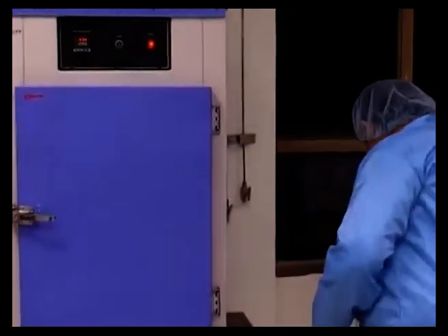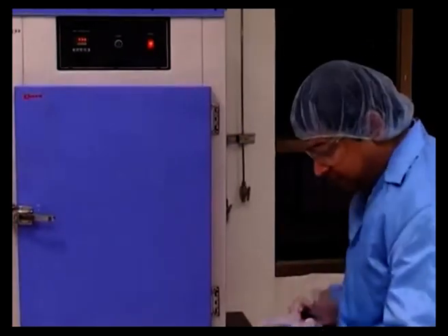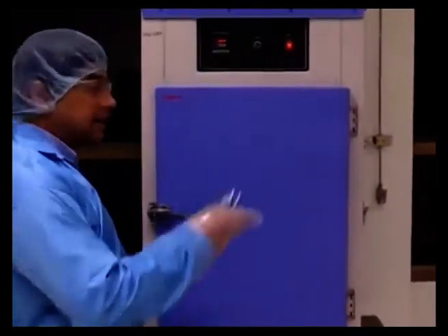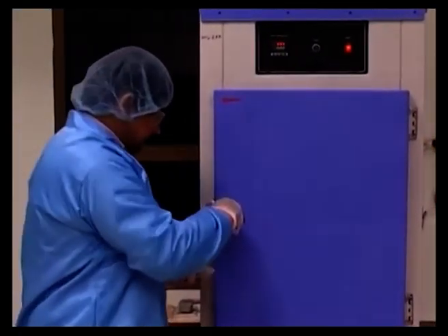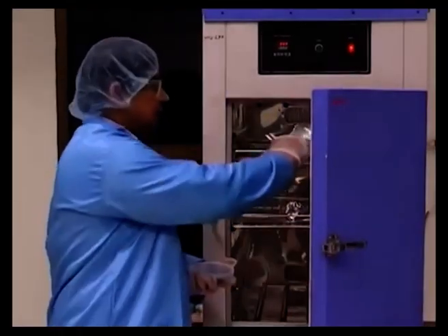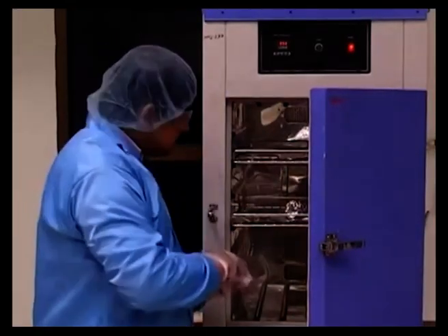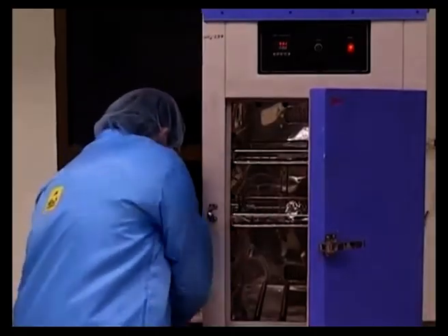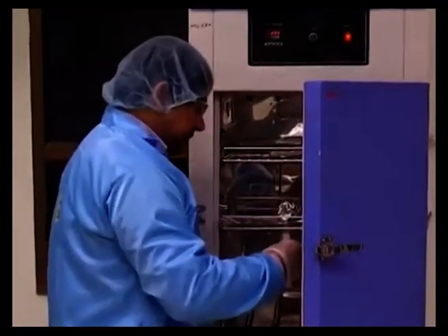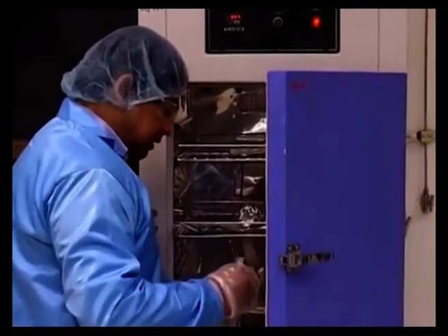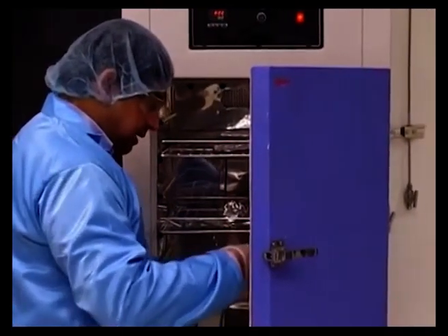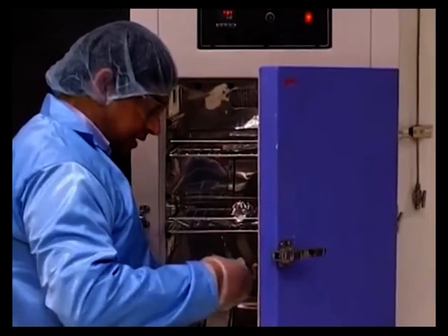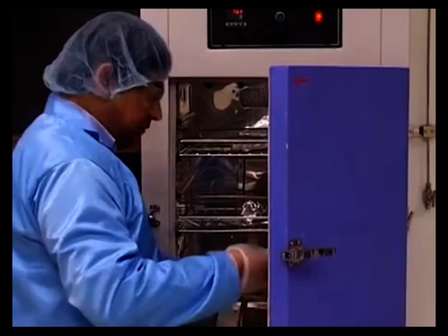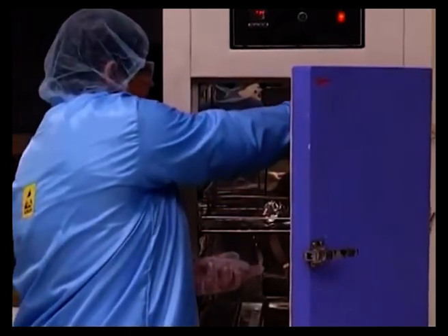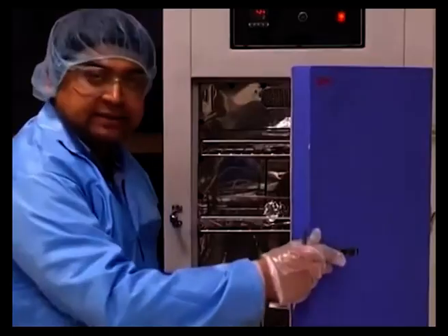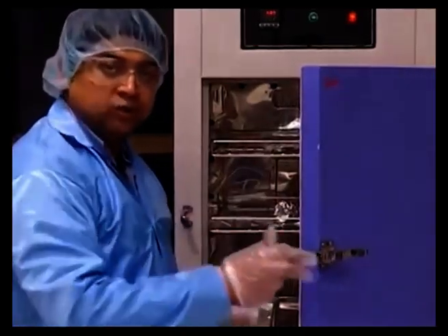So what we do is take the wafer box which we pulled out of the fume hood after the Piranha clean, put an aluminum foil on the top of one of these shelves, and then slowly load our wafer sample so that we can get it heated and remove any water present on the surface of this wafer. The whole idea is to have a perfectly dehydrated surface of this wafer, so that it is good for adhering to the photoresist that we spin coat on top of it before doing photolithography.